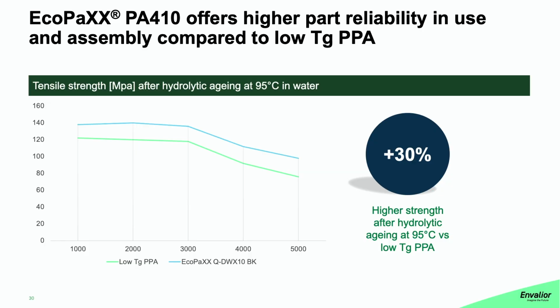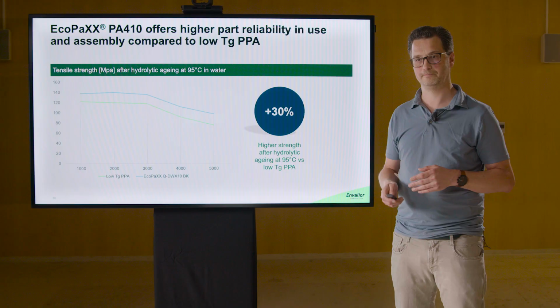EcoPax QDWX10 shows about 30% higher strength after hydrolytic aging at 95 degrees in water. And that's compared to a low glass transition temperature PPA. So EcoPax allows designs with thinner walls or higher torque in assembly or higher bending strength with the same dimensions.